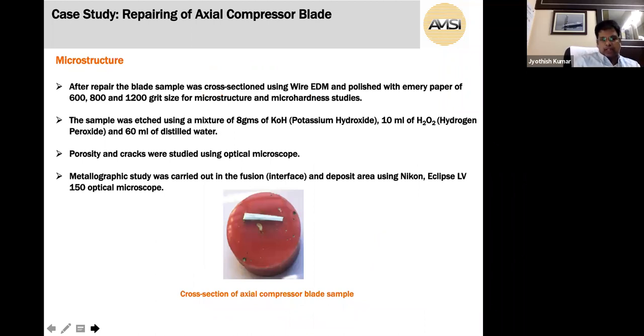After deposition, we did a lot of studies, such as microstructure studies. We did the cross section of the blade, and we studied various aspects. Before microstructure studies, we had to do a lot of preparations, such as cleaning the surface to have very good visibility of the microstructure of the inner portion of the deposition. Then we did optical microscopy to study the metallurgical bonding between the layers after the deposition with the base material.